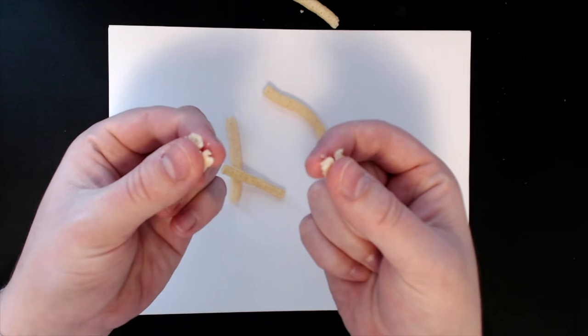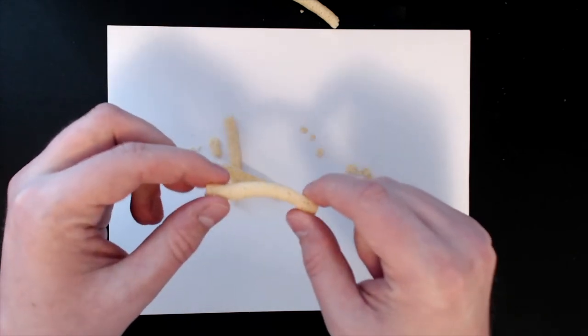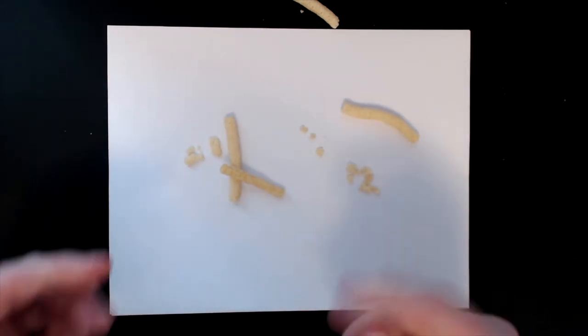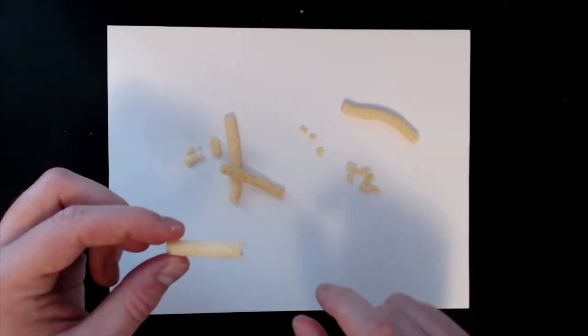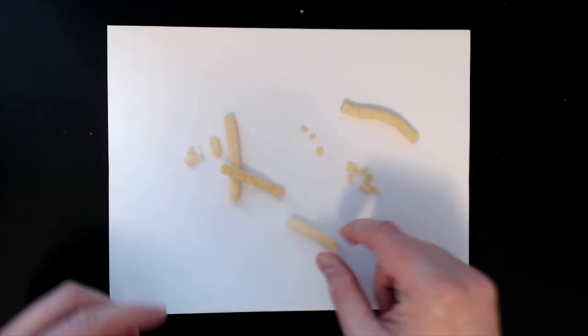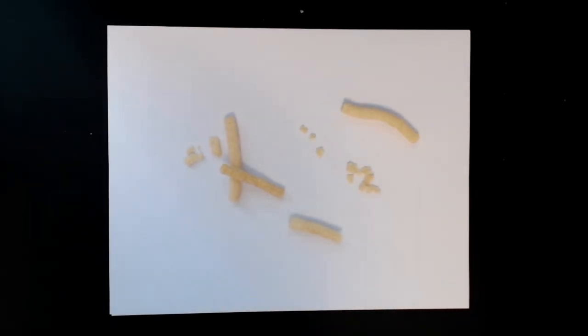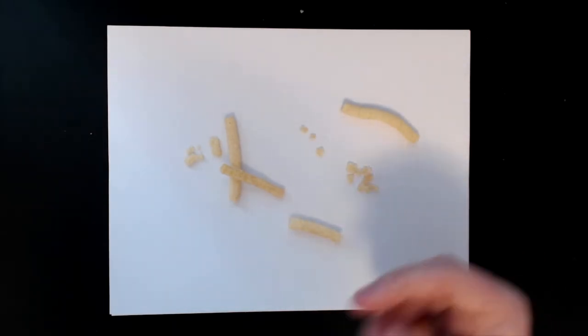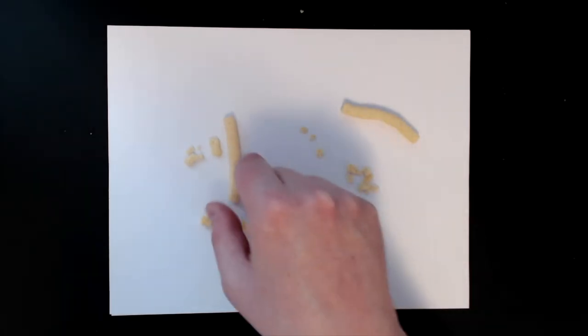You notice it's hard to do that. It's hard to pull it apart because you have to press down really hard on this area, which is akin to the grip area of your tensile dog bone. This is true of ceramics: they're really difficult to test in tension. They're typically not tensile tested because, as you can see here, I just crushed it where the grips were. I didn't really test it effectively. Ceramics are difficult to grip because of the properties. It just shattered into a million pieces. This is not a viable test.